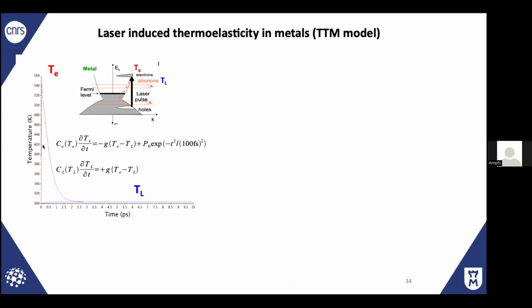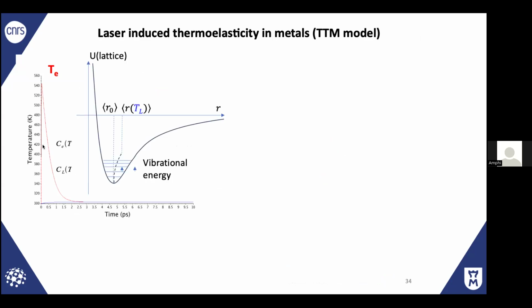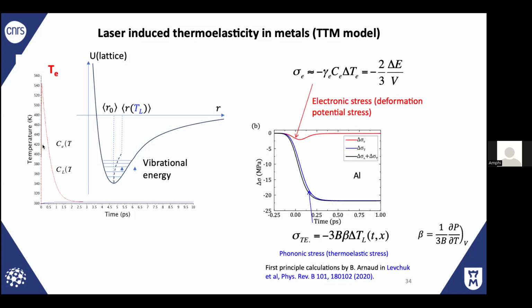So the deformation potential is one mechanism. Thermoelasticity is something that people asked about a couple of minutes ago. It's just due to thermal expansion. When you shine light, you excite the electrons, so they come back step by step by phonon emission, through electron-phonon coupling. If you have such a transfer of energy from the electronic level to the lattice level, it means you increase the vibrational energy. Since lattices are anharmonic, the average positions change, as you know: thermal expansion. Thermal expansion, beta, in thermodynamics is related to the variation of the pressure. It's simply what we call the phononic pressure, phononic stress. And this is exactly what you can compute in the Sommerfeld model.